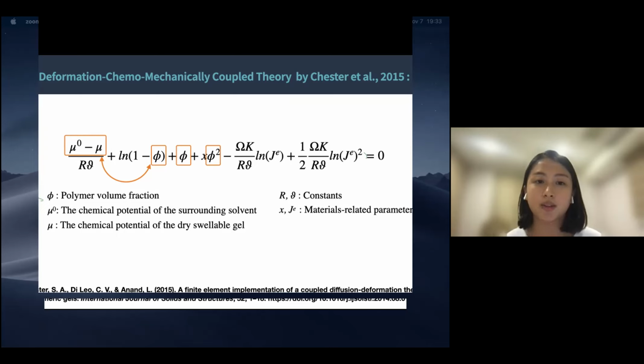So we use a theory called the deformation chemomechanically coupled theory. It's adopted from Chester. And it's a complicated equation, but we just have to focus on two parameters, which are the gradient of chemical potential between the surrounding solvent and the dry hydrogel, and then the change of the volume fraction. So in every time increment during the calculation, the difference of the chemical potential between the surrounding solvent, which we use water, and the hydrogel inside will have a corresponding polymer volume fraction.